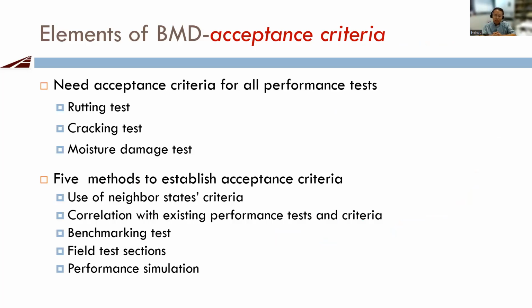After you choose the cracking test, the rutting test, the moisture damage test, you pick up your aging protocol, then you really need acceptance criteria for mix design. We need acceptance criteria for rutting, for cracking, moisture damage. There are 5 different ways to establish acceptance criteria. The easiest way is just using your neighbor state's criteria, like Oklahoma using Texas, or Arkansas, or any other state you think can represent your state.